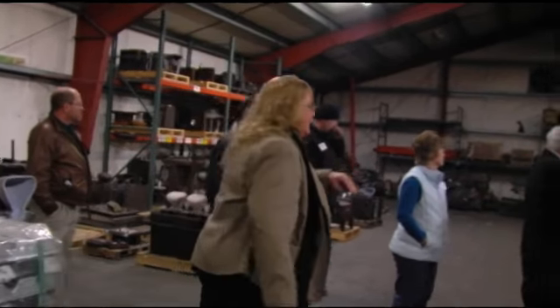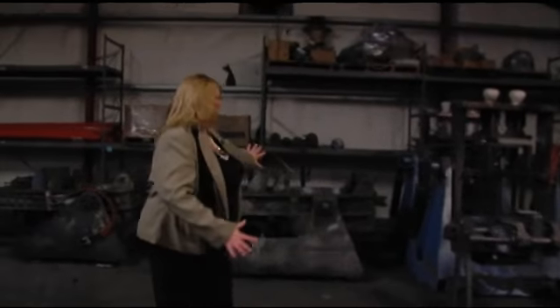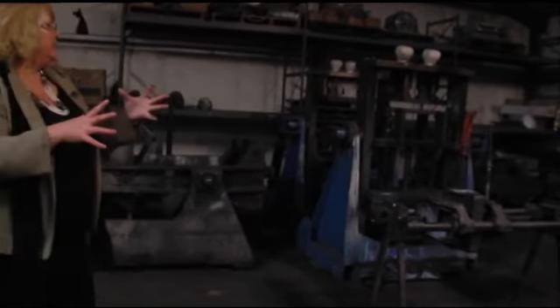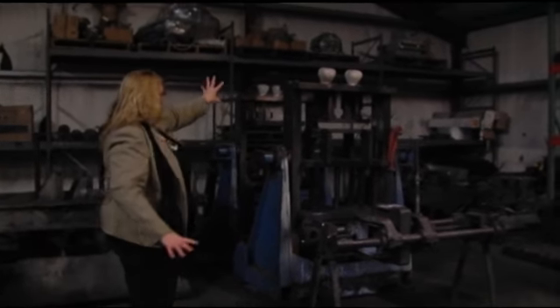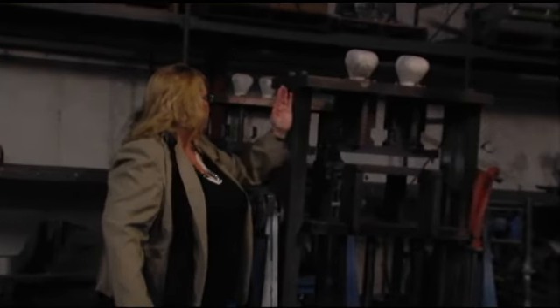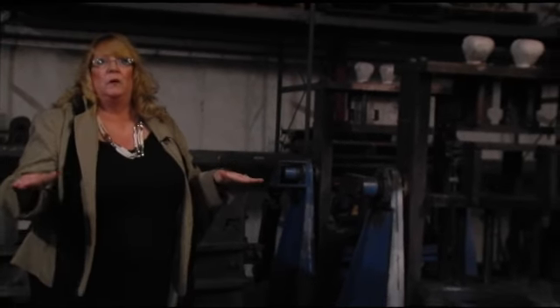A couple years ago, we also got into a different type of casting for us. It's called reverse tilt. The difference is you can see a lot of these open like this. They're just a regular sandwich. This one opens like this. But how we design the gate and the riser, so this comes down and then the aluminum's poured in slowly. This process was developed for wheel makers because anything with a heavy center and thin walls, this helps it push that aluminum out through those thin walls.